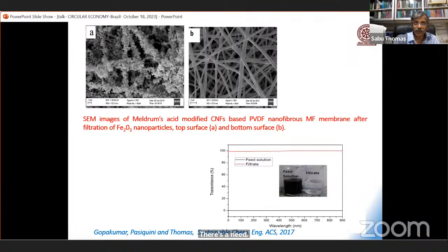But then we filtered this water through the filter. The top surface is PVDF coated with nanocellulose. You can see all these iron oxide particles have been stopped at the top surface of the filter. How? By absorption. This is the bottom part of the filter, which is made of PVDF. So we have shown that we can remove all these something very interesting. And you can see this is the pure water and this is pure water.